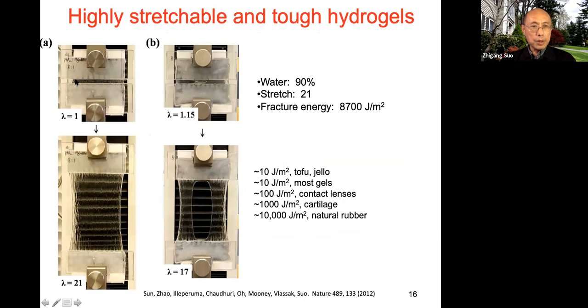So the hydrogel is this big, and we grip it with the two plastics, and then we pull this 21 times. It doesn't fracture, has a rubber-like feeling, right? And remember how we measure toughness. We need to make a cut and pull this again until the crack pops ahead. So when we do this with this material, we pull this 17 times, the crack doesn't pop, doesn't move forward. So that translates to toughness of almost 10,000 joule per meter squared.